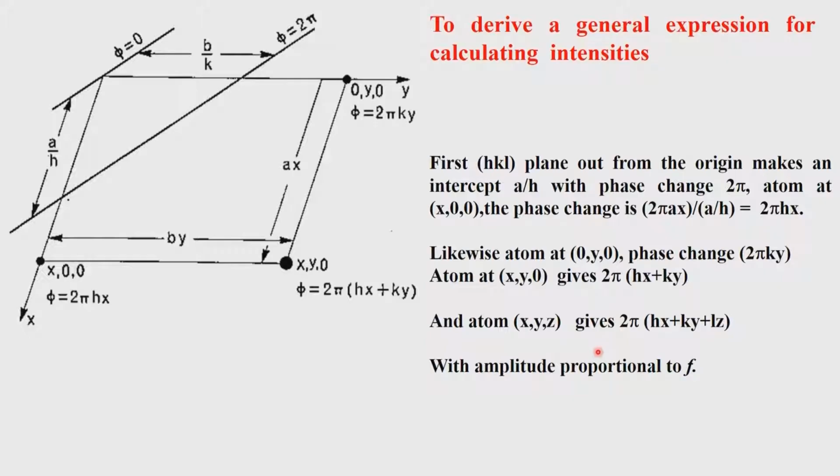So, what is important here is the location of the reciprocal lattice point. The location of the reciprocal point is associated with the plane, and the amplitude therefore has to be read proportional to that. So, whatever is the value of f at that particular corresponding scattering angle, which is corresponding to sin theta by lambda, has to be read out, and then we substitute it to calculate the intensity.